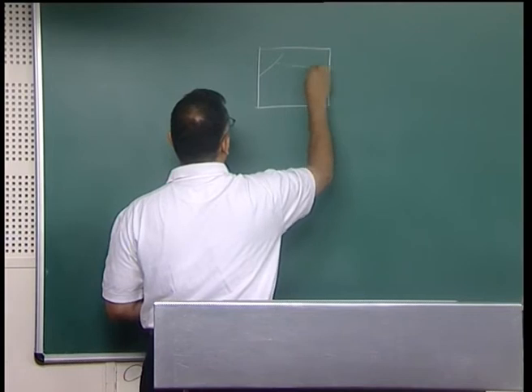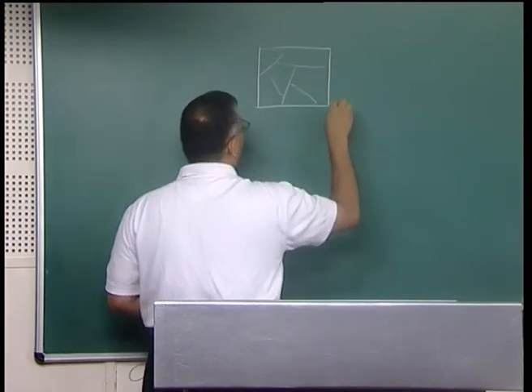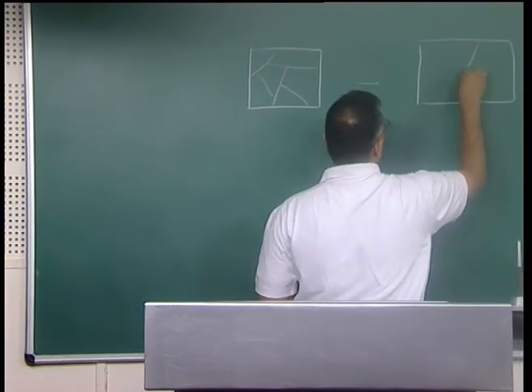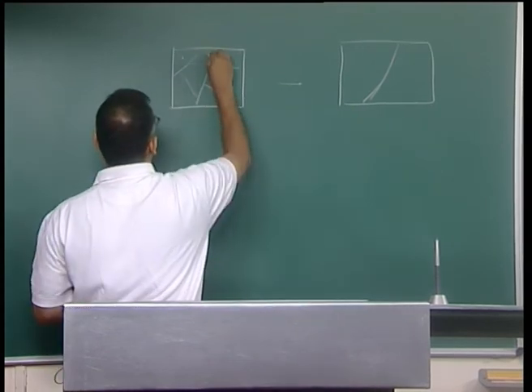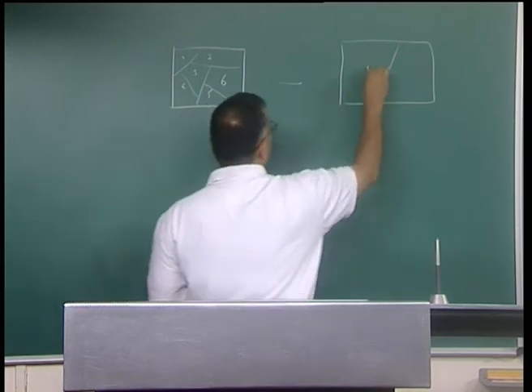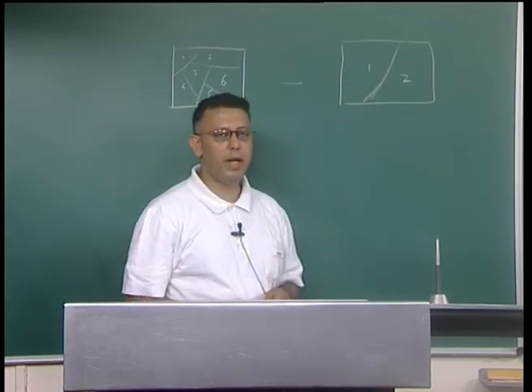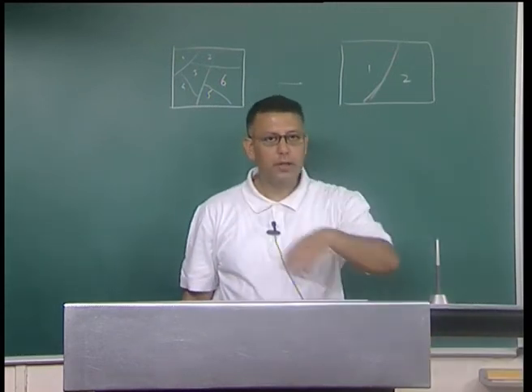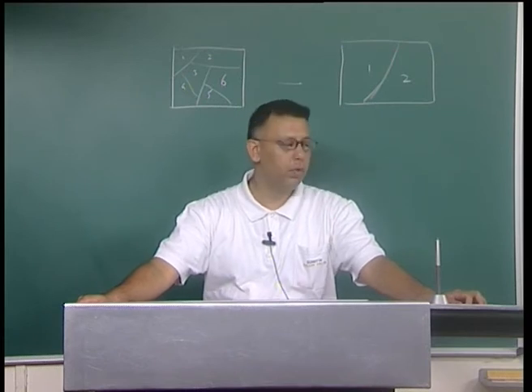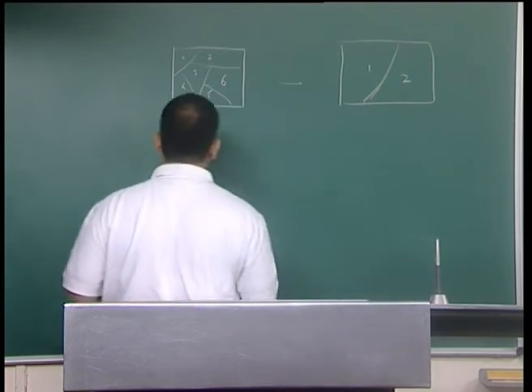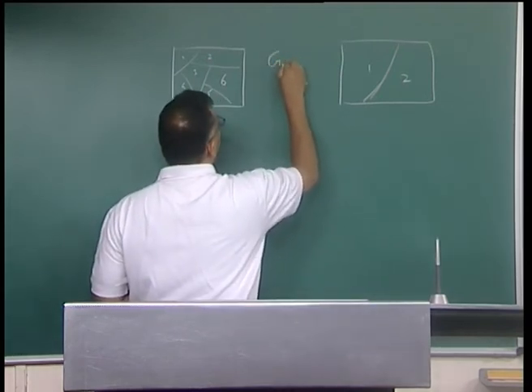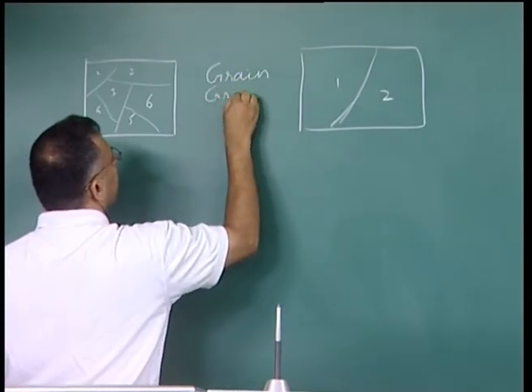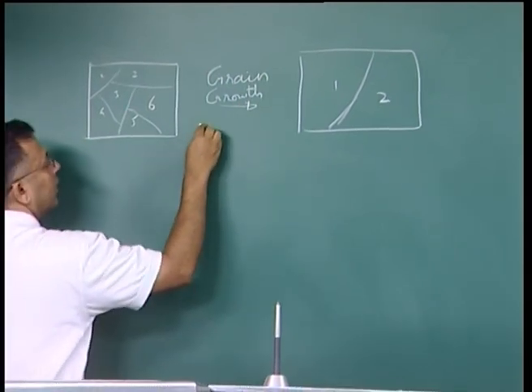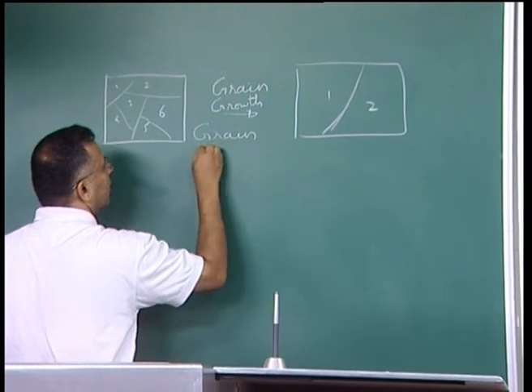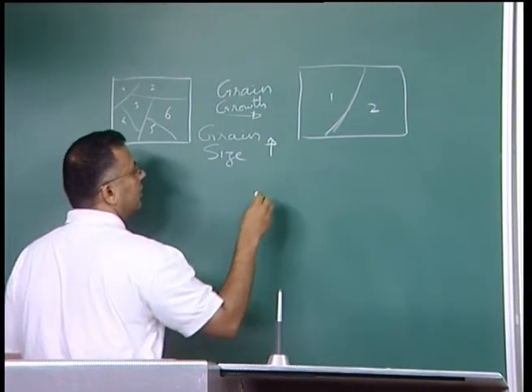Initially we have, for instance, a fine grained material, which could of course be a recrystallized material. So, I have my grain structure, and after grain growth I would notice that my grain size has increased. For instance, there were so many grains in this place, 1, 2, 3, 4, 5, 6, and I have only 2 grains in this place. So, grain growth implies that my average grain size increases. That means the grain boundary area per unit volume decreases. The grain size increases, number 1.